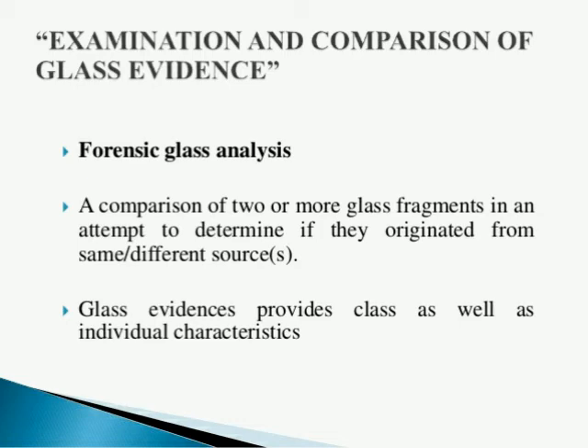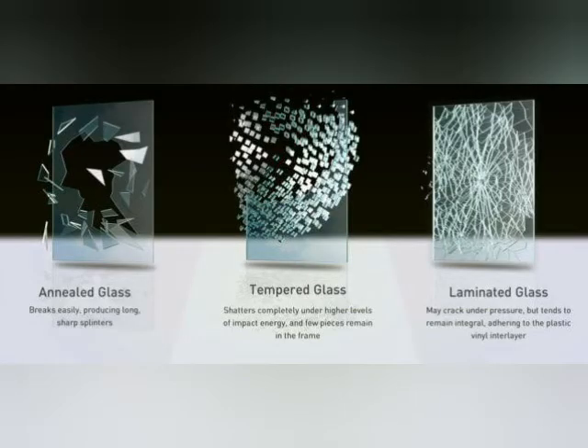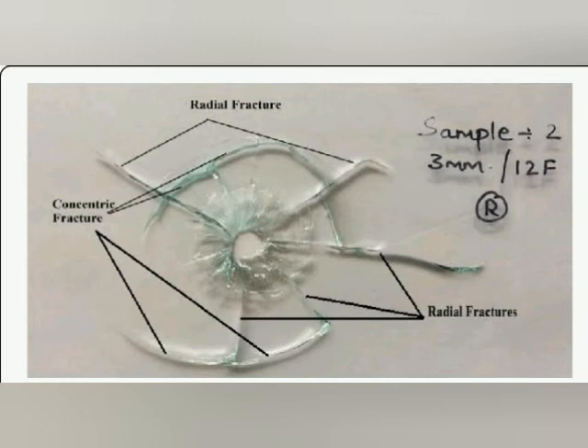There are various techniques for examining glass. We can go for microscopic examination using various microscopes like stereo microscope, polarized microscope, scanning electron microscope, mass spectrometer, and X-ray fluorescence. There is one technique known as the Becke line method, which is used for determining the refractive index of a glass sample. In it, the glass sample is put in a liquid and a halo of light in the shape of the glass is seen, which is known as the Becke line. When we move the objective lens, the Becke line moves towards the medium having the higher refractive index.